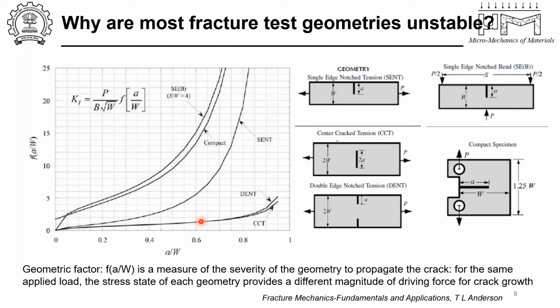So that tells me that the severity with which this bending geometry will cause a crack to grow will be much higher than the one for the DENT or the CCT specimen. Basically, for a given material with a material property of K1C, the fracture load for a SENB specimen is going to be much lower than the fracture load for the DENT or the CCT specimen. So one cannot make sense out of the fracture load; one has to make sense of the fracture toughness that you get. In a way, the geometric factor is a measure of the severity of the geometry to propagate the crack. Each of the stress states will cause a different magnitude of the driving force for crack growth.